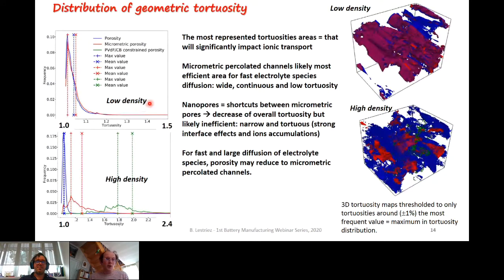They are plotted here for low density and high density electrode, in blue for the total porosity, in red for the micrometric porosity, and in green when it was measurable or when the calculation could be done, because this phase was large enough. It is plotted also for the CB-PVDF mixture, the porosity within the CB-PVDF mixture. So the first conclusion is that the CB-PVDF nanoporosity is much more tortuous than the other. It is more tortuous than the micrometric porosity.